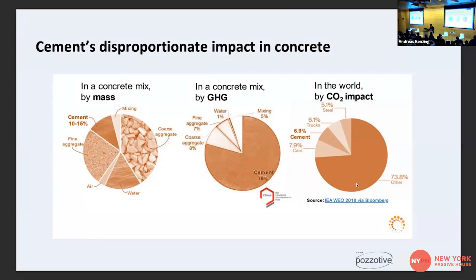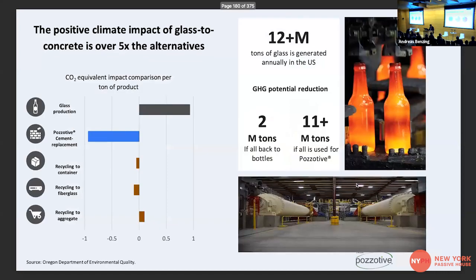So with ground glass pozzolan, it's a pound for pound replacement up to 50%. And it depends on what you're trying to achieve with your mix designs, right? So there's that opportunity, and there's opportunities to create ternary blends. That's a mix with other pozzolans or other supplemental cementitious materials. We're actually going as high as 70%, with a 35% replacement with glass pozzolan, 35% replacement with slag, and 30% of OPC. So big opportunities to really create dramatic carbon reduction for concrete.